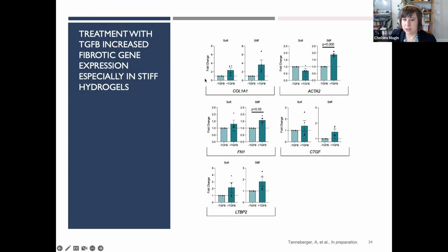So we can see here, if we're looking at the fold changes of these genes, this is collagen 1, and ACTA2 is the gene that controls alpha smooth muscle actin. We see significant increases when we add TGF-beta in the stiff microenvironments. We also see changes in fibronectin production, latent TGF binding protein 2, and then also CTGF, which is a measure of a growth factor, connective tissue growth factor. So all these changes indicate that both our microenvironment and the biochemical cues that we're giving the cells allow us to create a fibrotic model using human cells and human tissues.